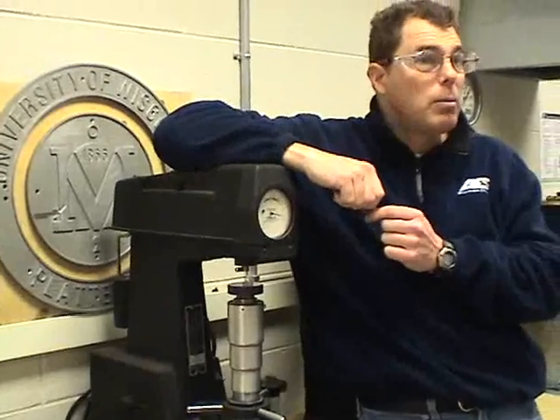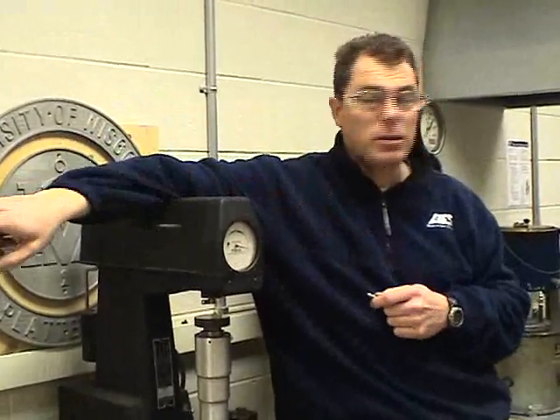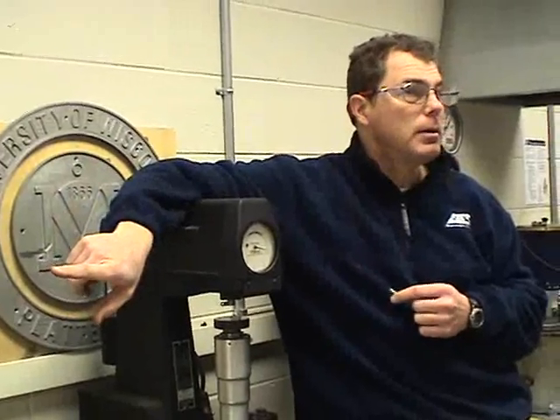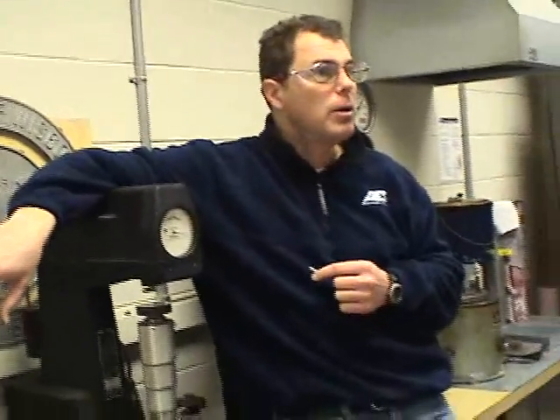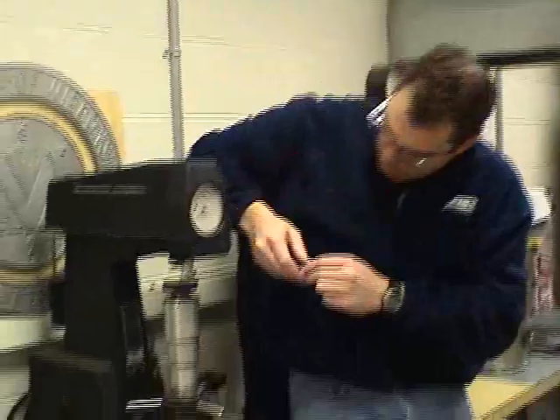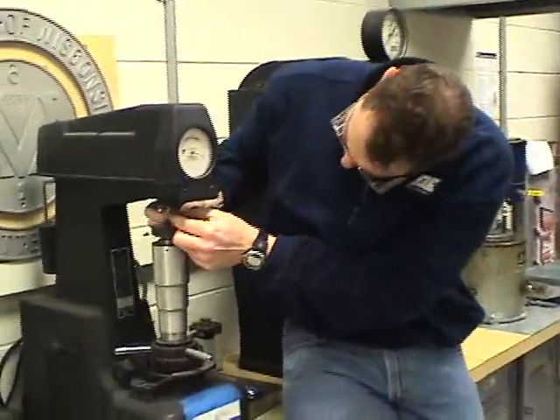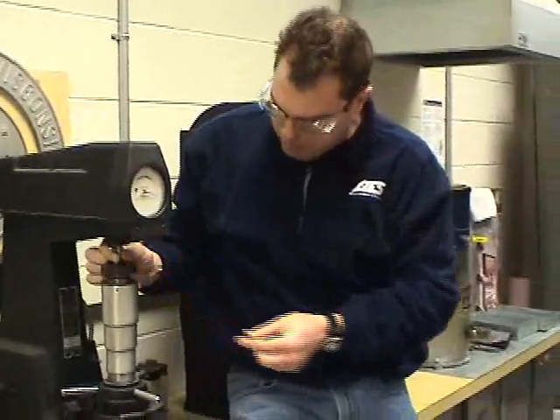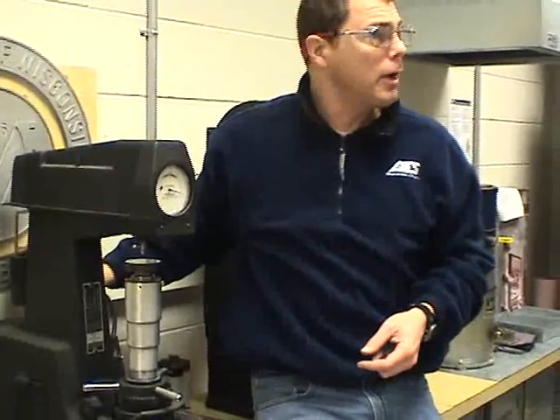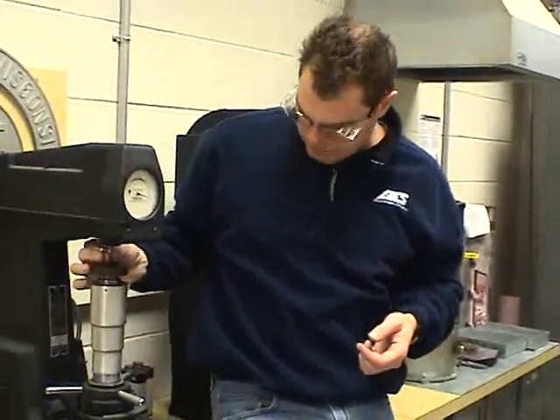What's low? Well, below 20 Rockwell C, which is this scale, it's not accurate. So anything below 20, it'll give you a hardness number, but it will not be a very good one. Because what happens is basically the diamond has completely embedded itself into the steel, or whatever material you're testing, and you've gone past where the diamond is. And so on the 1/16 inch ball indenter, we use 100 kilograms load, and it's a bigger surface area. So now it's for softer materials.